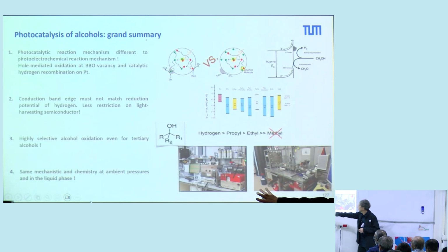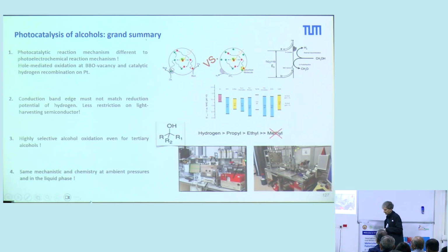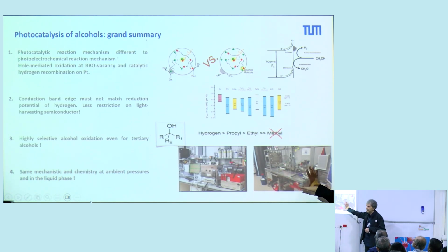Last but not least, what I didn't show you, we also performed these experiments at ambient pressures and in the liquid phase. And for methanol, we see a very similar product spectrum. That means we believe that also here, this mechanism can be applied.